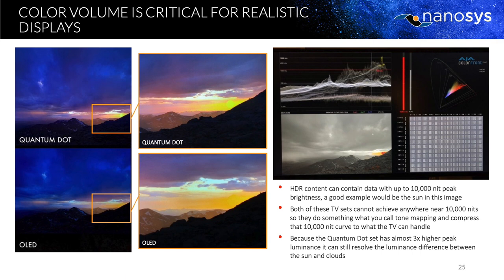What you would want to do is for whatever code value input, you want that to go all the way up to 10,000 nits. Well, displays can't do that. Even a Hollywood mastering monitor goes up to about 4,000 nits. But you can still see a big difference because of the higher brightness of the quantum dot display versus the OLED display in its ability to show variation in these higher luminances. And so these tone mapping functions are important, and it underscores the importance of driving to higher brightness in a display as well as higher color gamut.